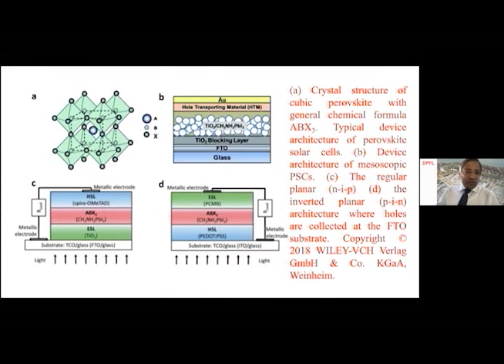So this is the NIP configuration, where the electrons are extracted through the conducting glass on the bottom side. At the same time, if you look at the other configuration, the PIN, the electron transport layer on the bottom side, on the transparent glass side, is reversed to the top side. And here we are putting a hole extraction layer on the conducting glass side. So this is the only difference between the NIP and the PIN.